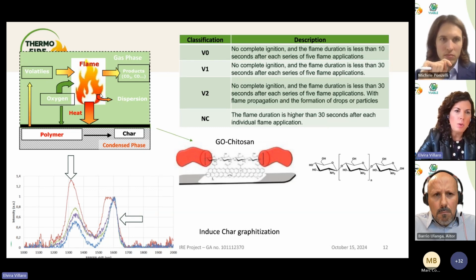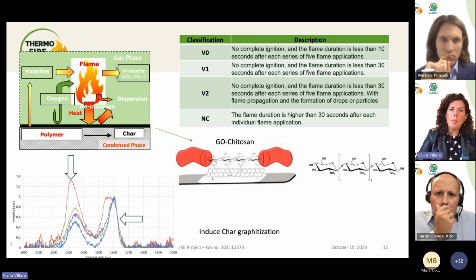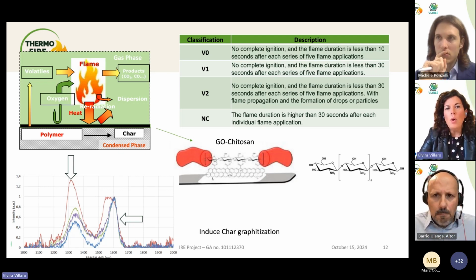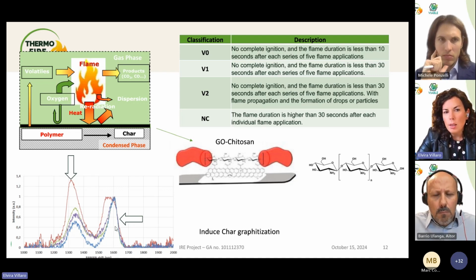But also we have other two effects, which are reducing the oxygen, because it can't permeate to the polymer, and also re-radiating the heat, because some of the materials that we are putting in have high thermal conductivity. So what we are doing is analyzing the char areas, and we see that some of the materials we put in at the beginning, for example graphene oxides, have this intense band, which is associated with the defects, the oxide moieties that we have on the surface of the graphene materials.